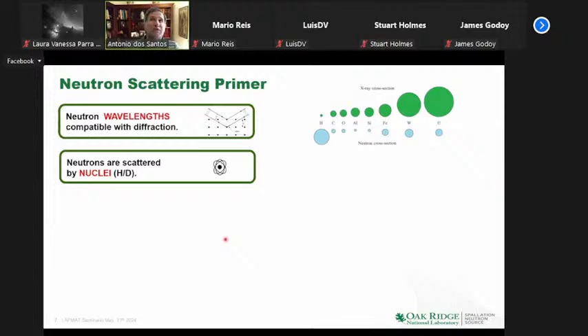But the big contrast with other radiation sources is that neutrons are scattered by nuclei, which means they have very different cross-section ratios between elements than when you do X-rays. So if you want to study a uranium carbide with X-rays, you barely see any carbon because the scattering cross-section is so much smaller. But with neutron scattering, you can really know what the carbon is doing. That is maybe one of the biggest advantages: you have truly a different way to contrast.